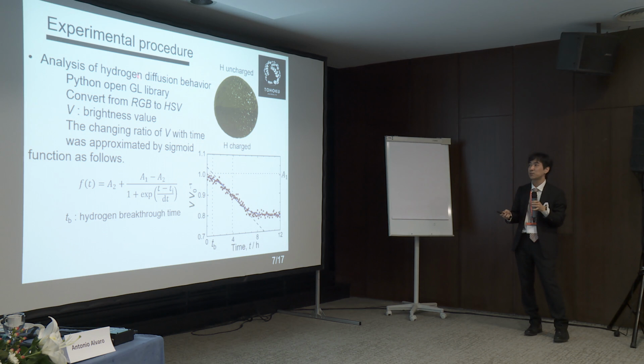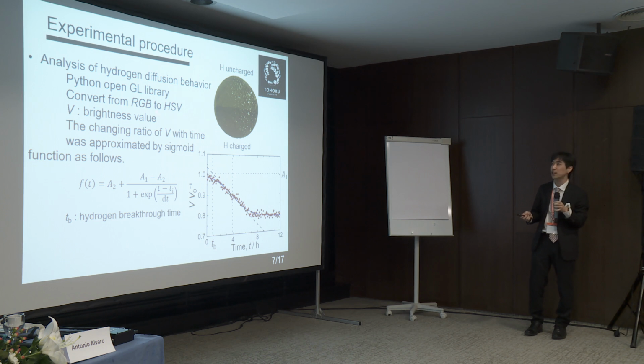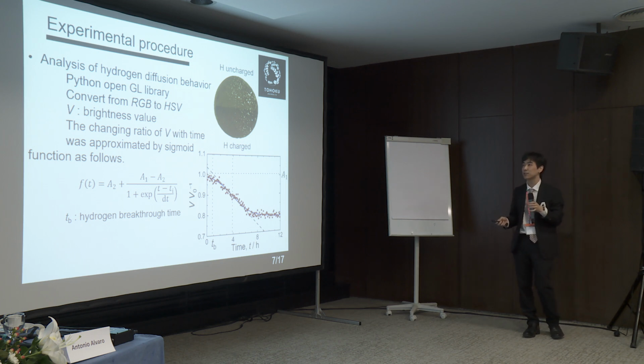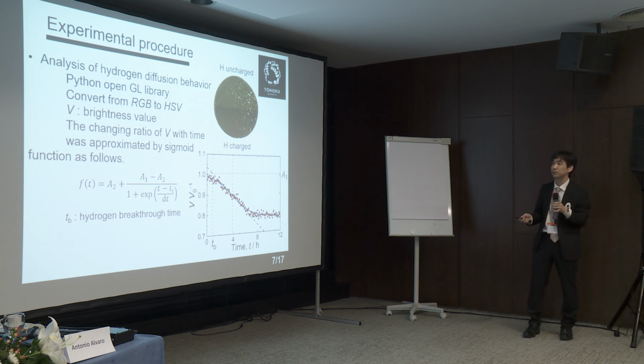The hydrogen diffusion behavior was analyzed by Python, and we obtained the RGB color values from the pictures and converted them to HSV color space. We represented the brightness value, and we focus on this V because the color of the iridium complex becomes dark by the reaction with hydrogen that permeates through the specimen.